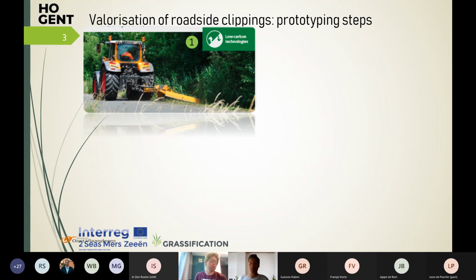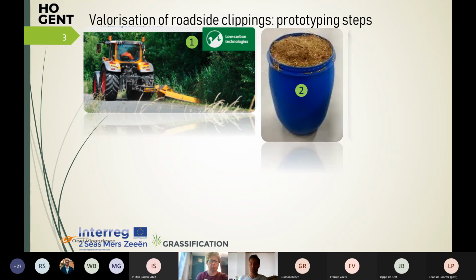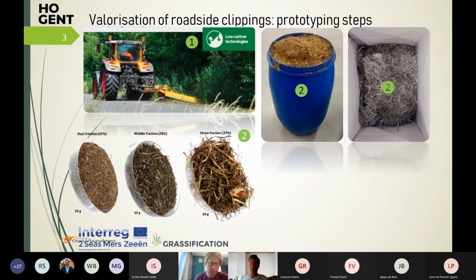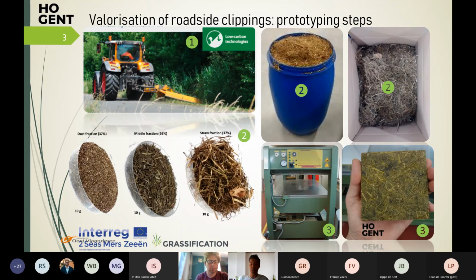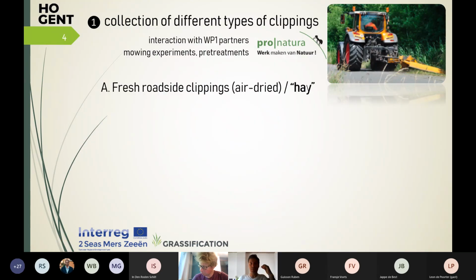For the prototyping experiments at the University College Ghent, we proceeded always roughly in 3 steps. We were dependent on the grass clippings that were provided by other partners in mowing experiments. So the grass was delivered usually in these blue barrels containing about 20 kilograms or 120 liters of grass fibers, which were moist depending on the type of grass. And then these were pre-processed, dried. We'll talk about this in detail in the next slide. And finally, we had the actual prototyping. Here's an example shown of a pressed fiberboard panel that was produced using the laminating press of the University College Ghent. So I will now go a bit into detail for each of these 3 steps.